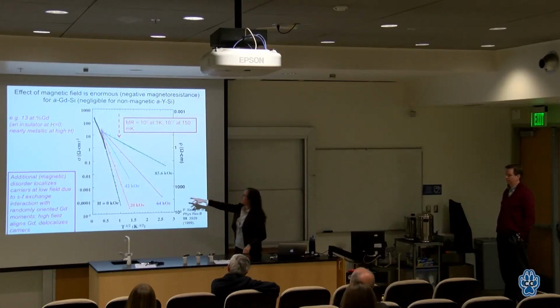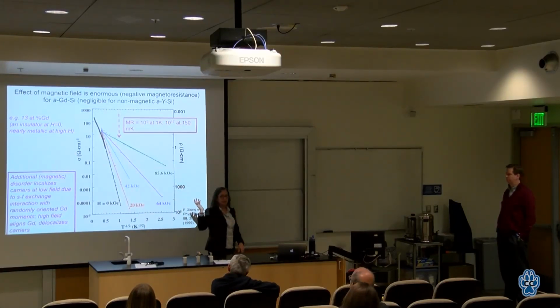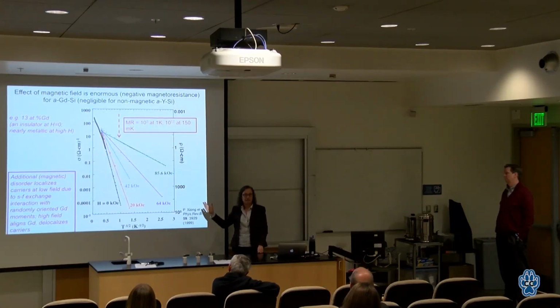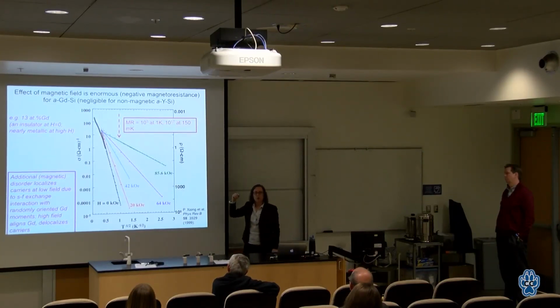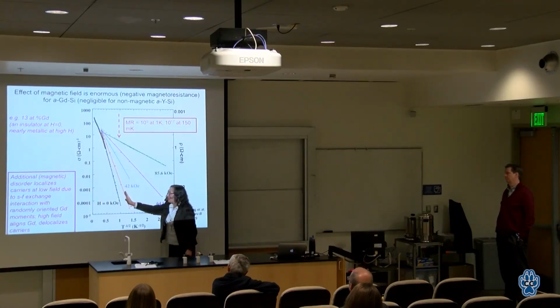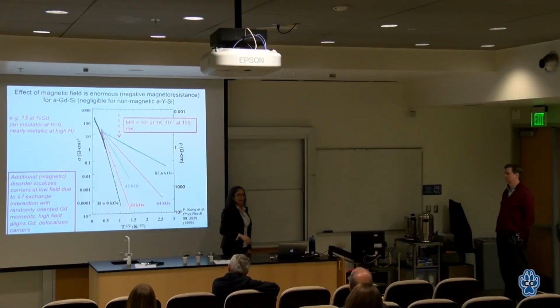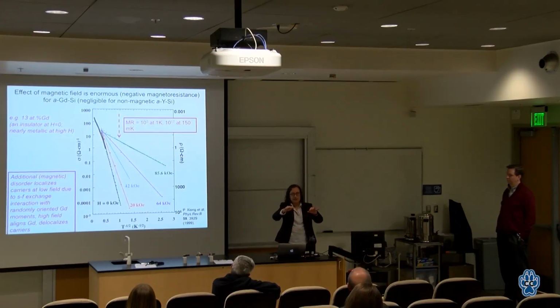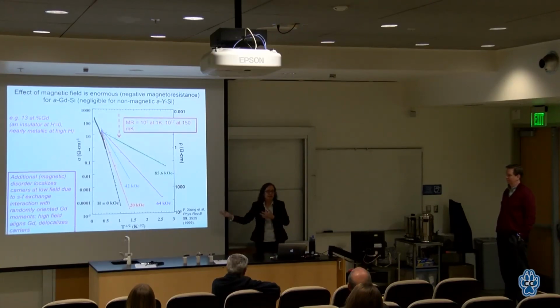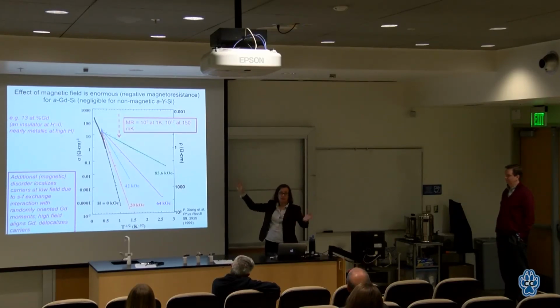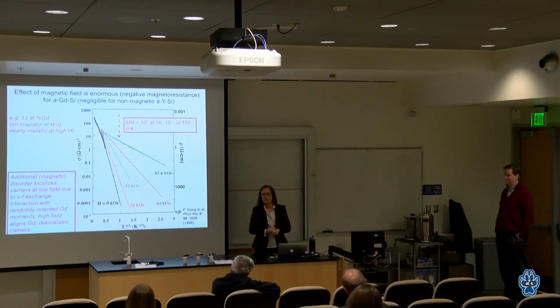I've gone past my plot. There's a very simple form for each of these. They have a T to the minus 1/2 dependence, which is exactly what metal insulator physics has. So I can explain each one of those perfectly in metal insulator physics. What there is no theory for is the way that T to the minus 1/2 changes. I can qualitatively say it's because I'm lining up the gadoliniums, but I can't quantitatively do anything with that. So it's sort of a hand-wavy Anderson localization. Each curve I can fit individually, and I literally can make them all collapse onto a single plot. But the collapsing variable has some dependence on how much these are lined up, for which there is not a theory.